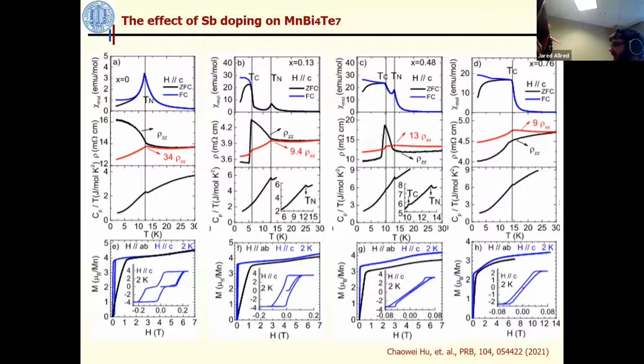Yeah, no, it does. It helps me to frame it all. So the point is that you come in with an idea about what your degrees of freedom are, but there's an extra degree of freedom you have to consider here. Yes, maybe more than 1 degree. Initially when we started this project, I never expected it to be such a big one. It turns out that it's not just a change of the local environment, they also introduce antisites, and then one more exchange interaction enters and makes it a little bit of a mess. However, it's interesting.